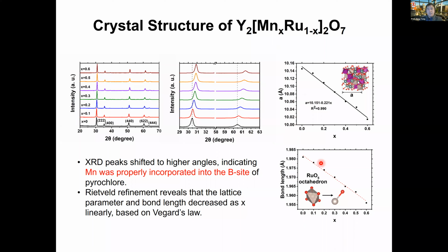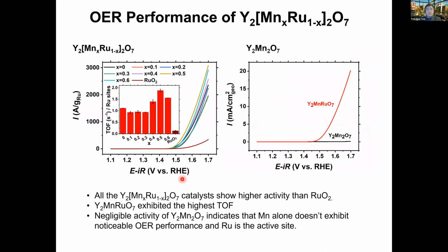If you combine all this information based on the Vegard's law analysis, this is good evidence of forming a very nice solid solution on the B site. So we can do this B-site tuning to a very large degree. What will be the consequence in this particular case? If you look at the per-mass-based analysis of this system, we can substitute the ruthenium, which is a rare, precious metal, by using the 3d transition metal in the first row without losing activity. In fact, when you normalize on the B site, it turns out that around the 50% range, we can obtain the highest performance for this particular type.